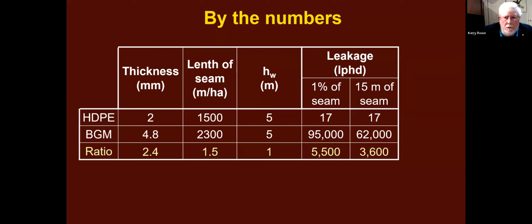If I do the same thing with the BGM, using the same data set we saw before, it's 95,000 litres per hectare per day. Now, you could say that's a bit unfair because 1% of 1,500 is less than 1% of 2,300. So let's compare them for 15 metres each. And you see 17, of course, for the HDPE and 62,000 for a BGM.